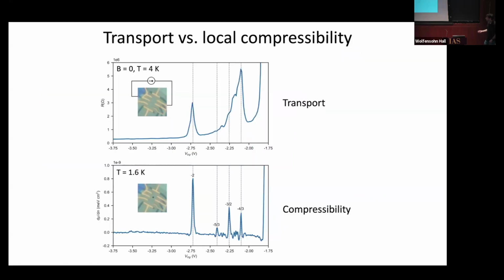So before I show you data from our scanning single electron transistor measurements, let me compare a transport measurement on the same device between these two electrical contacts. You can see, okay, as I go to more and more negative backgate voltage to hole dope the system more and more and measure the resistance through the sample, there are some peaks occurring here. Maybe it has something to do with Moiré physics, maybe not. This is a 4K measurement just at zero field.